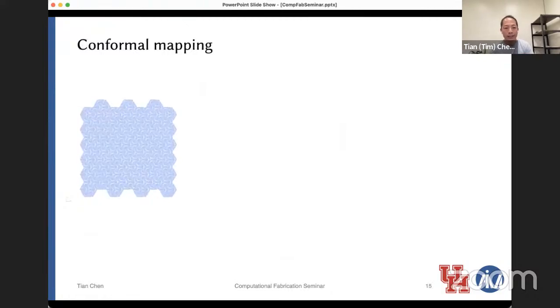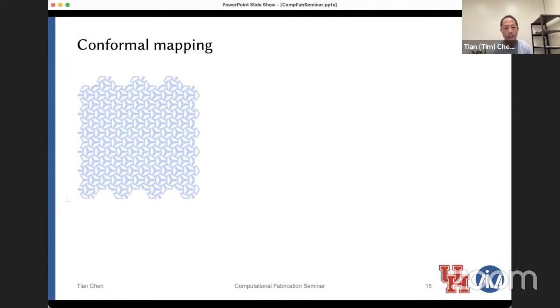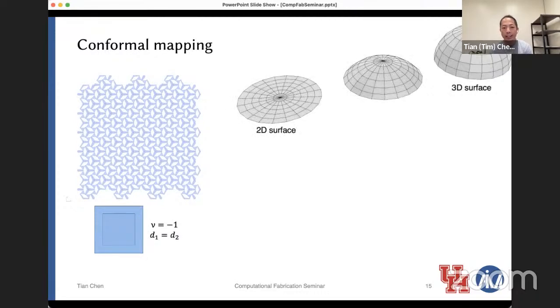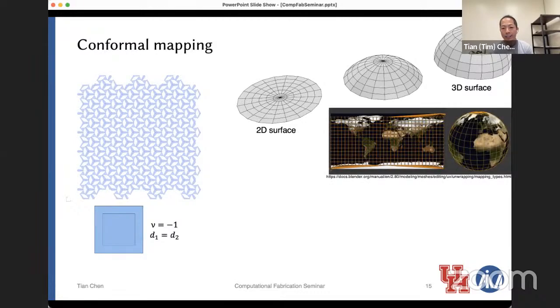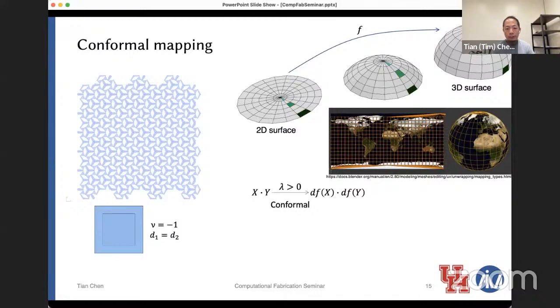As I said, if I tile the same unit cell everywhere, then I just get a planar expansion of the structure, which is not what we need because we already know how that works. But taking inspiration from cartography, where we can map a globe down to a planar surface, you see that due to the distortion, Antarctica and the north of Canada look much bigger than they actually are. We know that we need to change the area of each of these squares without changing the angles between the local elements. If we can satisfy this condition, then we say the deformation is conformal, and we can calculate the Gaussian curvature based on the difference in the length change of neighboring elements.